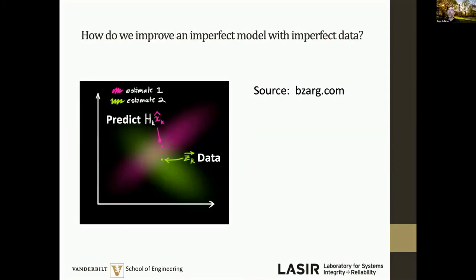But the challenge is that the model has parameters in it. And so like all models, these models have errors in them. The data also has errors in it because, like all data, data has errors when you're looking at the thermal response of this part. And so how do you address developing a technique that uses two inputs, to this inverse model that's a heat transfer model, and the thermal data on the surface, when both of those inputs have errors associated with them? So what you can use is what's called a Bayesian approach.